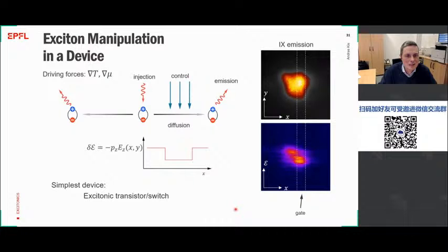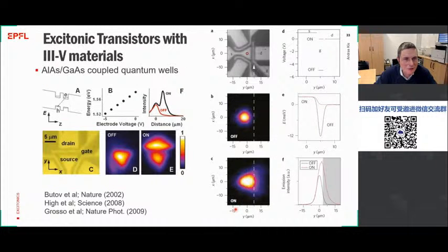Now, this idea has been around already for quite some time. So the first reports of so-called excitonic devices and transistors actually go back to 2001, but in those days, they were realized using 3-5 semiconductors grown using MBE and into heterostructures. And the problem was that due to the relatively low binding energy of excitons, these type of devices could not work at elevated temperatures. So the highest temperatures for the operation of excitonic devices was on the order of 100, maybe 150 Kelvin.